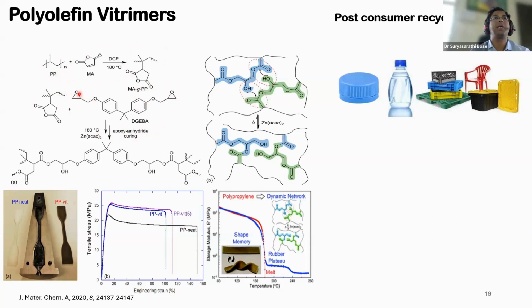And this is one example where epoxy was used to react with anhydride, which is called epoxy anhydride curing, and you have a dynamic bond. And this dynamic bond helps to improve the properties of the recycled material. This is polypropylene, which is neat, and the vitrimers have much higher tensile properties. But the question is whether they have the same MFI as that of neat PP. It's not reported in this study, but I'm sure getting to the same MFI requires a lot more than what you're seeing on the slide.